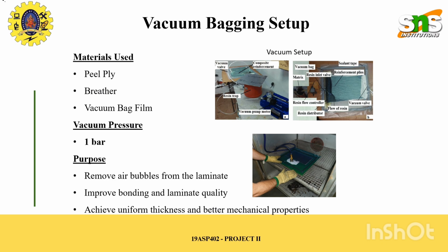In the vacuum bagging setup, materials such as peel, ply, breather, and vacuum bag film are used. A vacuum pressure of approximately 1 bar is applied to remove trapped air and excess resin. This process improves the bonding between layers, ensures uniform thickness, and enhances the overall mechanical properties of the laminate.